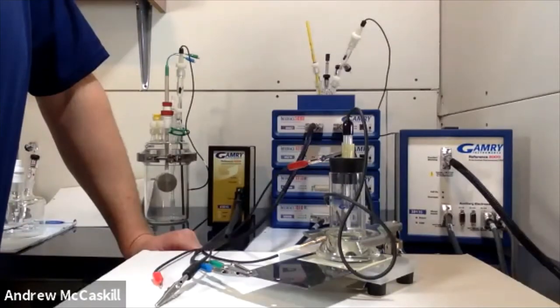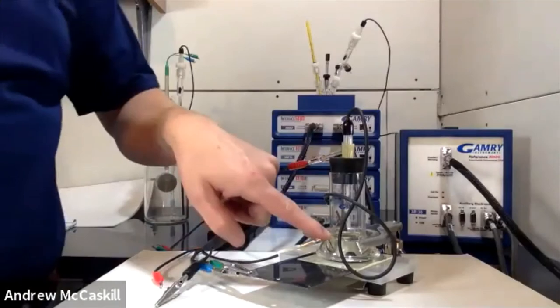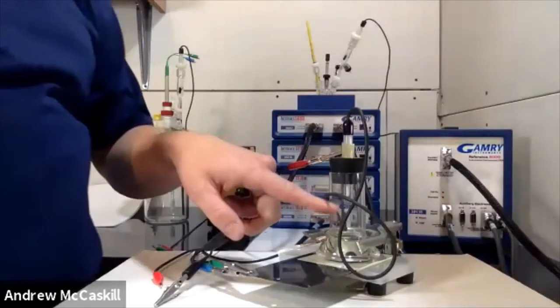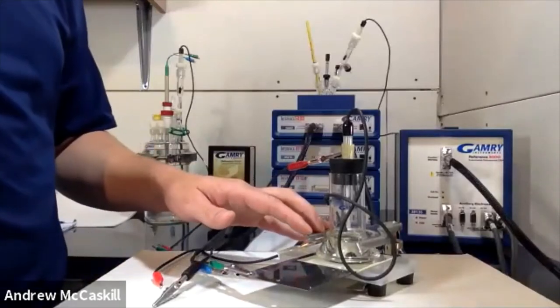If you're going to do very long-term exposure experiments on something that's corrosive, something that's gonna create a lot of corrosion products within this cell, start changing the concentration and the composition of the electrolyte, then this probably wouldn't be a very good cell for that.